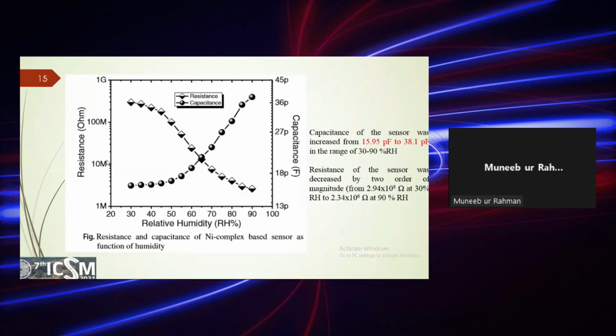This is the resistance and capacitive behavior of our sensor. When the relative humidity in the chamber where the sensor was placed is increased from 30 to 90 percent RH, the capacitance is increased from about 15.9 picofarad to 38 picofarad.